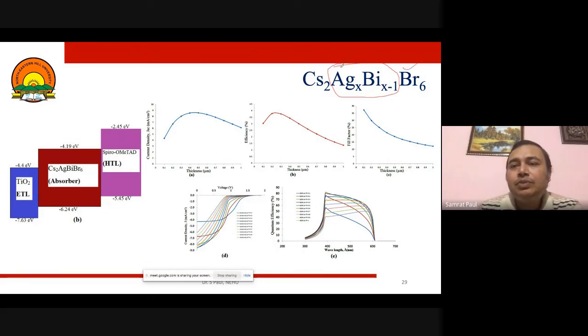And what we did is we incorporated, instead of the B site, since perovskite is ABX3, so double perovskite is A2BX6. So instead of B, we have put two different elements. So what happens if we change the ratio of these two different elements, how do they behave and how do they work? With this type of materials also, we did some thickness optimization for different materials, and we did spectral response also. And all these studies show that this is the normal IV characteristics of different materials.